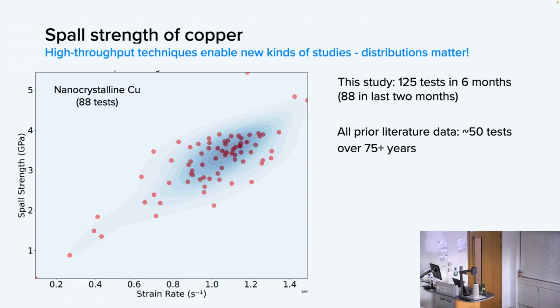So here's a set of 88 tests that were done. This is all on nanocrystalline copper, plotting out the relationship between spall strength and strain rate. I'll just point out, we did 125 tests, and by we, I should really say the group of Katie Ramesh, whose brainchild this whole thing is, did 125 tests in about 6 months. They did 88 in about 2 months. All the prior data in the literature was about 50 tests over 75 years.